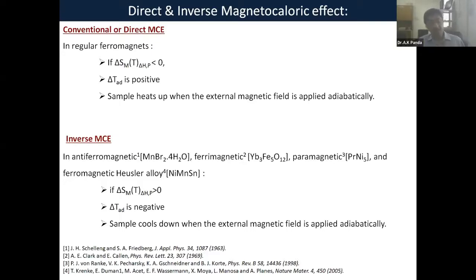What happens actually in this case is that the change in magnetic entropy becomes positive. Unlike the direct magnetocaloric effect, it becomes positive, and consequently there is a net effect on the crystal lattice, and you have a delta T, adiabatic, that is negative. This is in principle the difference between the direct magnetocaloric effect and the inverse magnetocaloric effect.